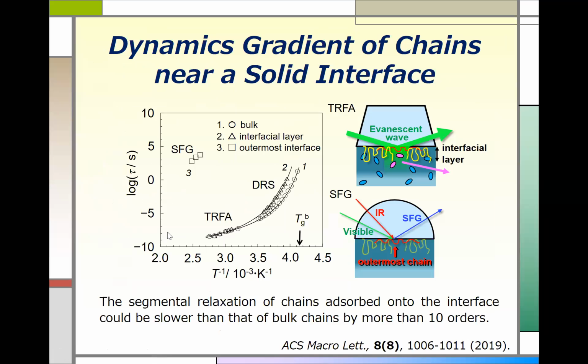This is actually the relaxation time of glass transition. And more concretely, this is the segmental motion, and this x-axis is the inverse of temperature. This is like the Arrhenius plot. And going this way, temperature is going to be higher. And here is the bulk Tg. And this is the bulk behavior. Number one is bulk behavior. And number two is the interfacial behavior with a thickness of 15 nanometers. And here is actually obtained by SFG.